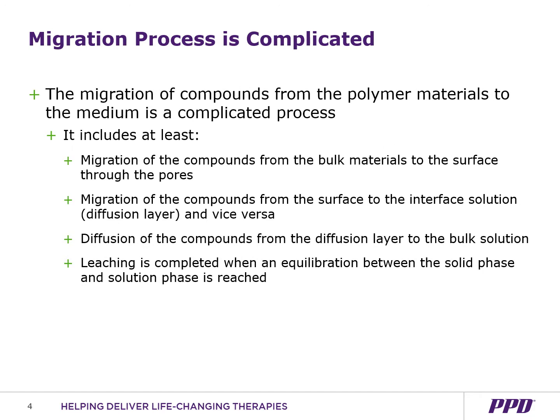Unfortunately, the migration process is quite complicated. There are a lot of factors that go into compounds migrating from polymer materials. Some of those factors are the migration of compounds from bulk material to the surface through pores in the material, the migration of compounds from the surface of polymer material to the interface or the diffusion layer and vice versa, the diffusion of compounds from the diffusion layer into the bulk solution, and leaching really isn't completed until an equilibrium is established between the solid phase and the solution phase. A lot of different factors go into the migration process, and I will touch on this again later in the presentation.